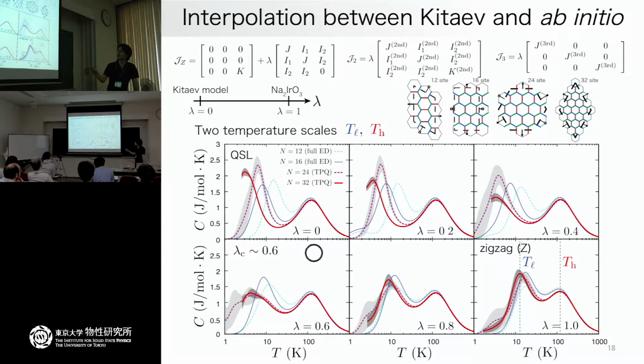Here, I will show you the heat capacity data for the Kitaev limit of the sodium iridate. And this is the ab initio limit of the sodium iridate. Here we have many detailed couplings together with the Kitaev component. So we just leave the Kitaev coupling in the ab initio Hamiltonian and scale down the other terms, like this. And then we can interpolate between the Kitaev model and the ab initio Hamiltonian for the sodium iridate by changing this scaling factor lambda. This corresponds to lambda equals 0, and this corresponds to lambda equals 1.